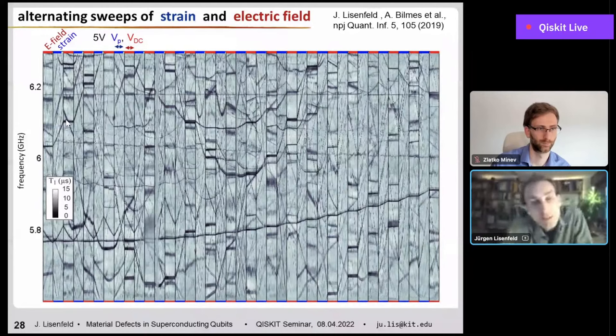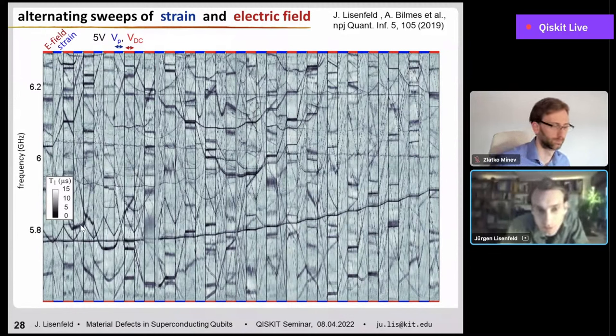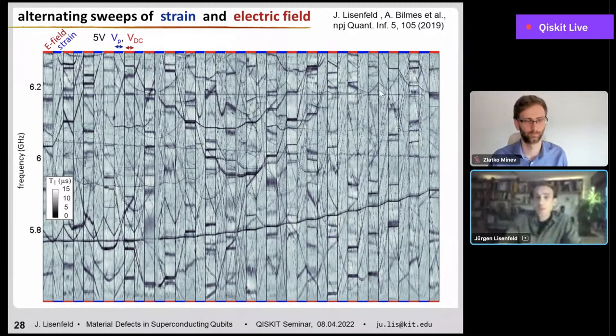And you see, defects in the junction don't couple to the field, but they couple to strain. So you get these staircase kind of signatures here, also basically staircase-type hyperbolas, if you wish. But you can also find defects on the surface, which are tuned by the electric field and by the strain. For example, this is a surface defect, which has a nice zigzagging hyperbola up to the very top here.